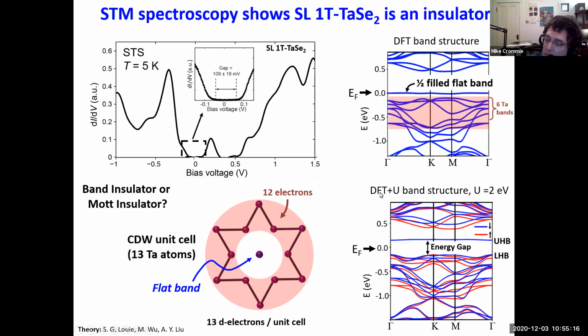And when you perform a DFT plus U calculation on this material, where you choose a U of 2 electron volts, which is commonly accepted for this material, then you do in fact get an insulator. A gap opens up, as you see here in this band structure down below.